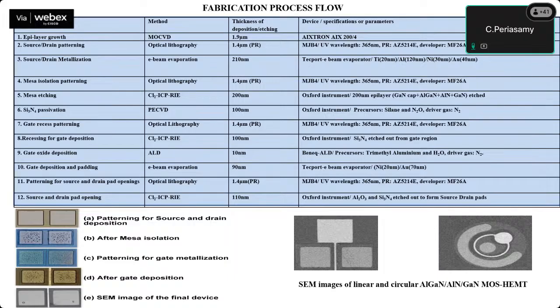And then for source drain patterning, we have used the optical lithography technique. To deposit source and drain, we used optical lithography with UV wavelength of 365 nanometer. To create that source drain patterning window, we have used optical lithography. To deposit the source and drain metal, we have used the e-beam evaporation method, and the source drain contact metal thickness in this work is 210 nanometer.